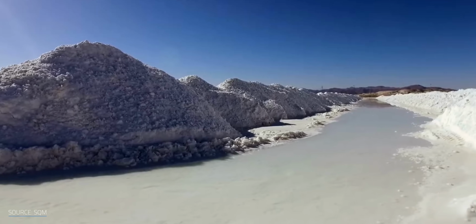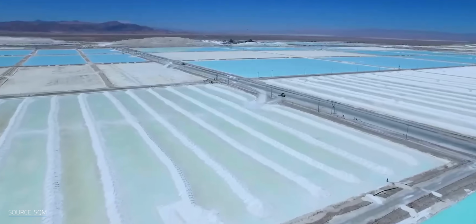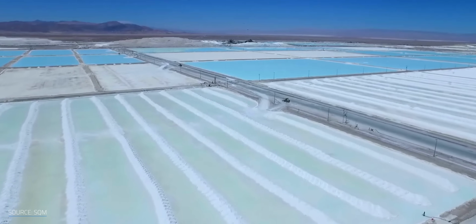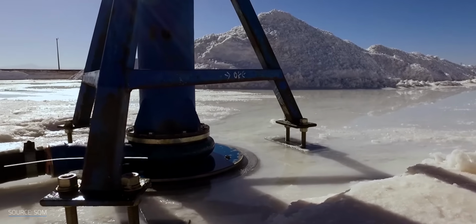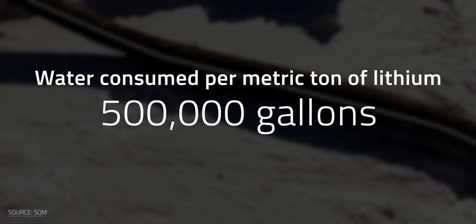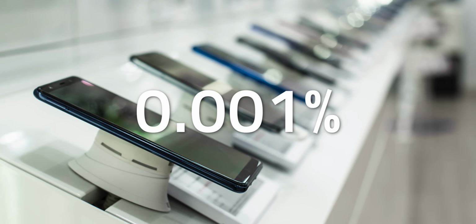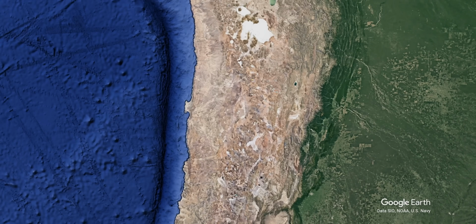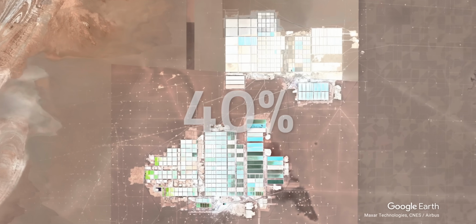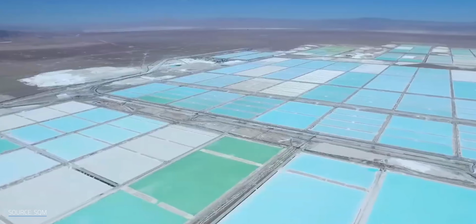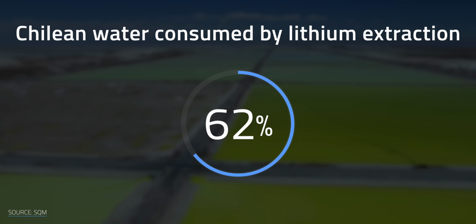For instance, you typically get lithium by evaporating water out of massive ponds containing a salt solution known as brine. For each ton of lithium that you recover, you lose around 500,000 gallons of water. To put that in perspective, that would only be enough to make batteries for 0.001% of all the cell phones in the world. In Salar de Atacama, a salt flat hosting around 40% of lithium global reserves, extraction drinks up 62% of the Chilean region's water. That's not the worst of it though.